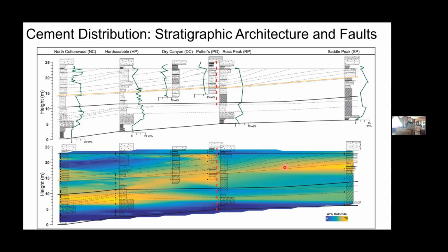And the bottom is exactly the same data, but it is linearly interpolated in MATLAB from outcrop to outcrop. And these surfaces, these clinoform boundaries or stratigraphic surfaces, were not used as bounding surfaces. So it's just strictly interpolating one point to another across the range. And so I want to bring back a couple of the points I mentioned earlier to discuss how the diagenetic alteration relates to those. So the first was that the lower shale thickened significantly from south to north. As it does, the total amount of TOC increases. And we see the highest abundance of dolomite in those locations where the lower and middle shales are thickest and most clay rich. Second was the relationship to that fault that I mentioned earlier.